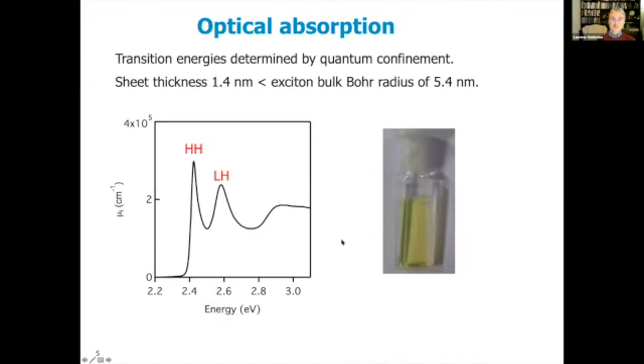Now, a little bit more about these nanoplatelets. We can dissolve them in hexane. They look yellow, and that's because their band gap is close to 2.4 eV. That is about 0.7 eV higher than for bulk cadmium selenide, and that is due to the quantum confinement. The bulk exciton Bohr radius is 5.4 nanometer. Our sheet thickness is only 1.4 nanometer, so you squeeze the excitons to be flat, and that gives rise to